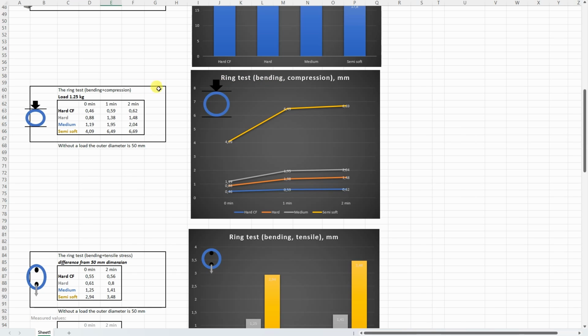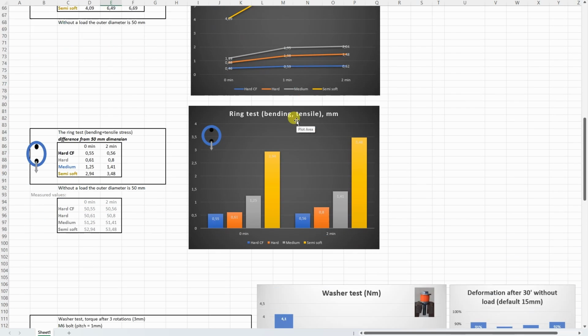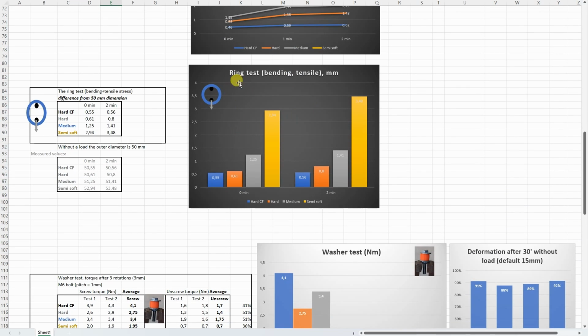The ring test, with the bending and compression, and I measured here the deformation after 0, 1 and 2 minutes. And here the biggest deformation I can see with the semi-soft filament, but what is important here is that this line here is almost horizontal. This means after 1 minute the additional deformation was very minimal. Something similar we can see on the bending and tensile ring test. Here the biggest deformation is on the semi-soft material, but here I measure only after 0 and 2 minutes.